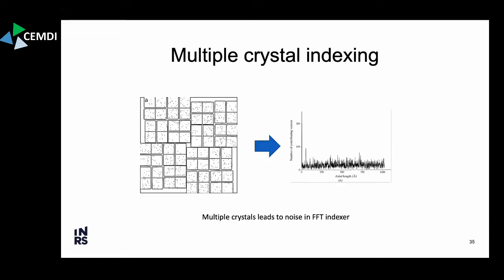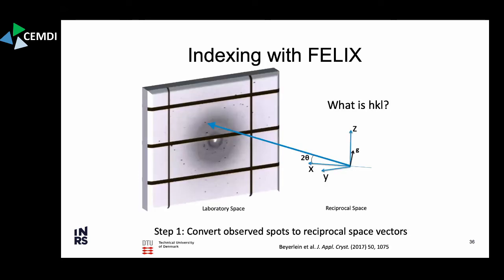But when you have multiple crystals in the diffraction pattern, it again looks like noise when you take this Fourier transform, because you don't have as much correlation. You have too many competing orientations to allow you to use this Fourier transform algorithm. And so I worked with some colleagues at the Danish Technical University, Søren Schmidt, namely, to develop a new algorithm in order to solve this problem and to be able to index these multiple crystal diffraction patterns.